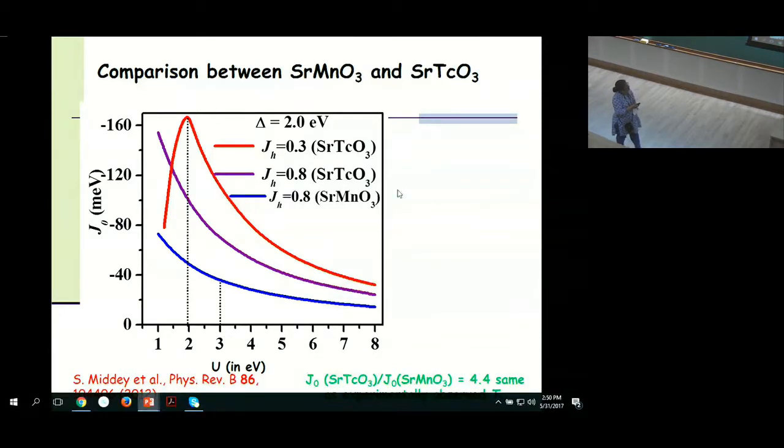But what's most surprising is that the model predicts that for the 4D oxide, the Néel temperatures lie on this curve over here, much higher than the 3D counterpart over here. We also get this regime where, in the superexchange regime, the Néel temperature, if dominated by the first nearest neighbor exchange interaction strength, would vary as 1 over U, and we have that dependence. And in the low U regime, we have a dependence which increases almost linearly with U. And so you have this peak.